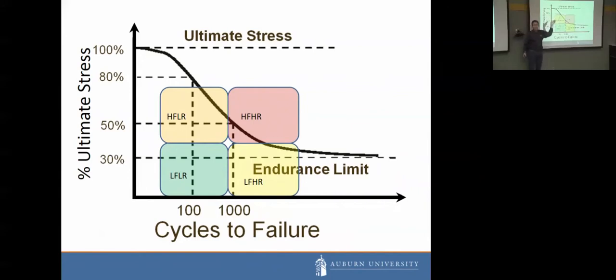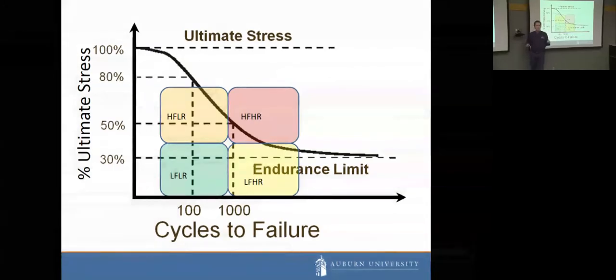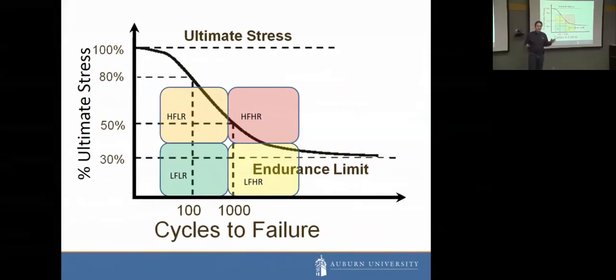You can still get that material to fail, whatever it is, at 80% of that ultimate stress level, but it may take 100 cycles or so to do so. And if you lower it to 50%, maybe you go 1,000 cycles or so, and so forth. And if you get low enough, obviously, you're going to be able to go many thousands, hundreds of thousands, millions of cycles. And for many materials, there's an endurance limit somewhere around 30% where you can keep loading it pretty much indefinitely. Musculoskeletal tissues don't necessarily show this endurance limit, but we've got healing on our side.